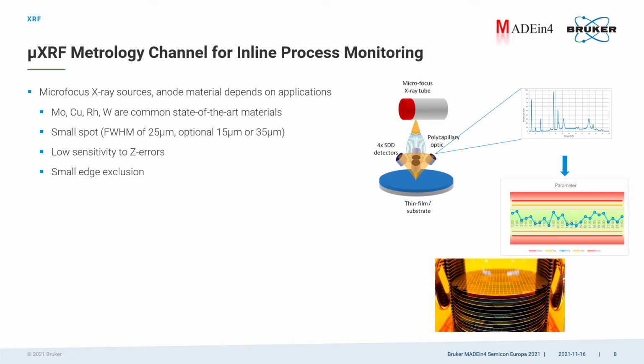So micro-XRF is a technique that perfectly lends itself to inline process monitoring. On the right-hand side, you see the typical flow of how micro-XRF is used in the fab on production wafers. The wafers are routinely measured on specified measurement pads or devices. The Bruker tool converts the obtained spectra, which you see here, into meaningful data for the customer, for example, the thickness of a specific film. This parameter is then sent to the fab host, where it will be tracked to ensure that the production is within the required process specs.